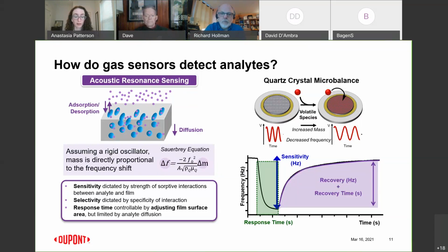So this is the kind of data that I'll be showing on the following slides. We have on the y-axis the frequency of that oscillation. The bare substrate has a higher frequency, and as mass absorbs to the substrate, the frequency slows, and you get this shift in frequency based on the difference in mass of the oscillator. In the green box, we're adding mass to the oscillator, and then it equilibrates at some lower frequency. But then if we flush the system with some sort of clean gas like nitrogen, we'll have desorption of those species, and we'll recover the original frequency from the bare substrate.